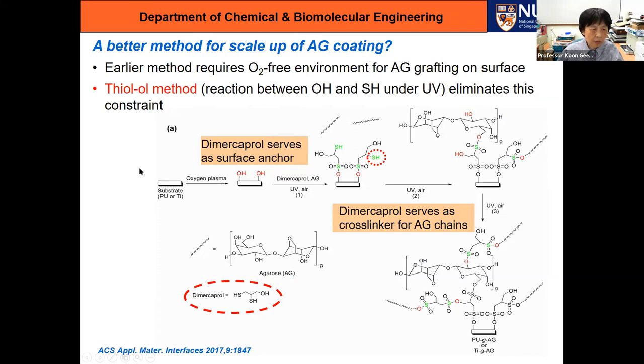So here we again have the substrate where we introduce surface reactive groups using plasma. And then we need a linker. And this linker is dimercaprol. Dimercaprol is shown here. It has two thiol groups and one OH group. It is an FDA approved agent for treating heavy metal poisoning. So it's a good thing to use. So what we do is now to use dimercaprol to react with the surface group. So the thiol group will react with the OH surface groups, and the remaining thiol will be used to react with the OH of the agarose. And agarose has lots of OH, so that's not a problem. And then further reaction with dimercaprol and agarose will give us a cross-linked coating.